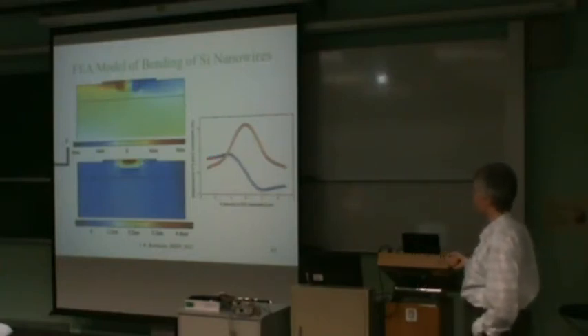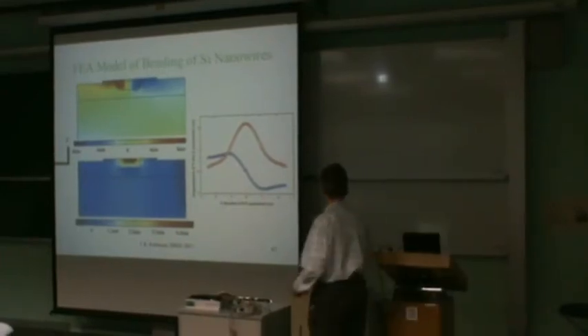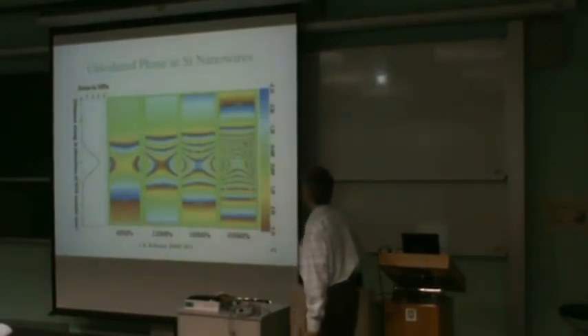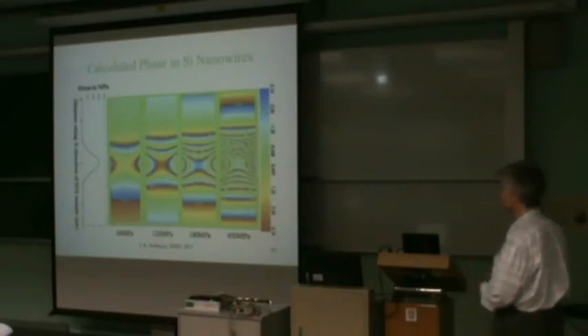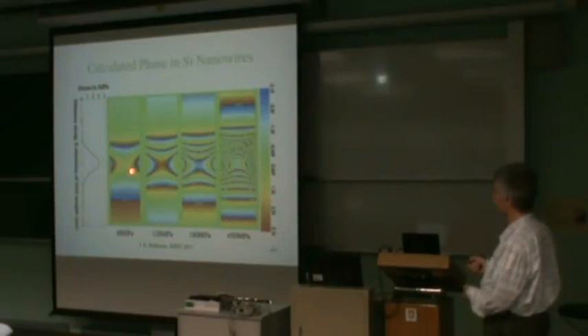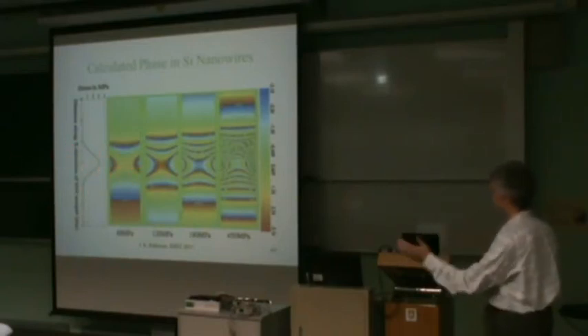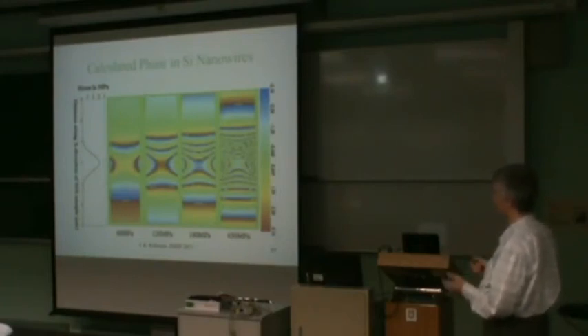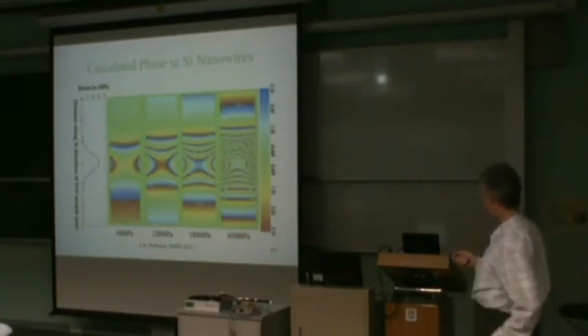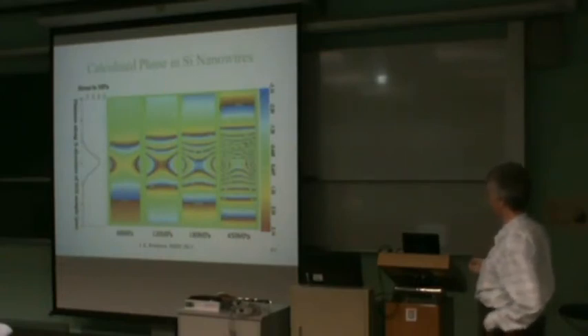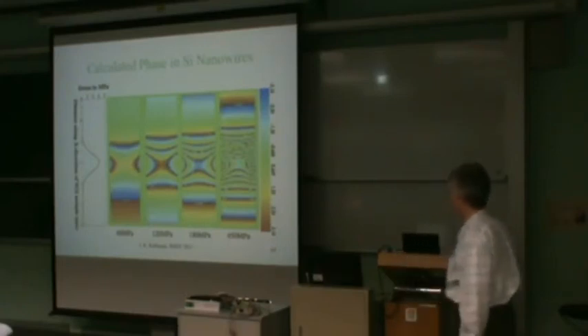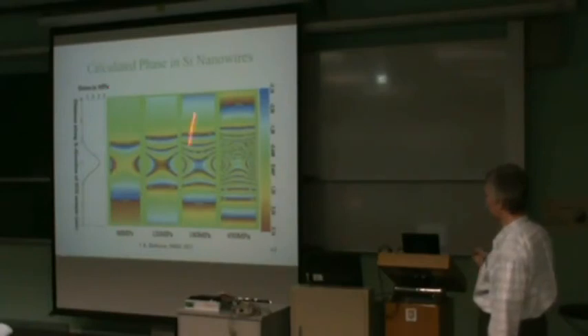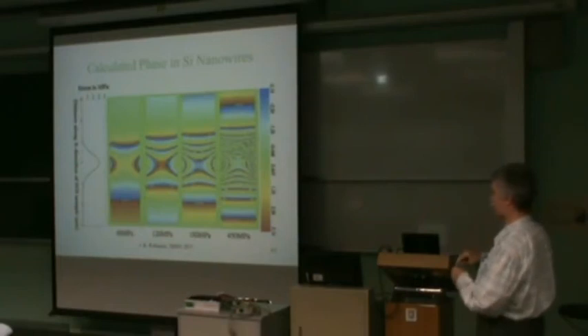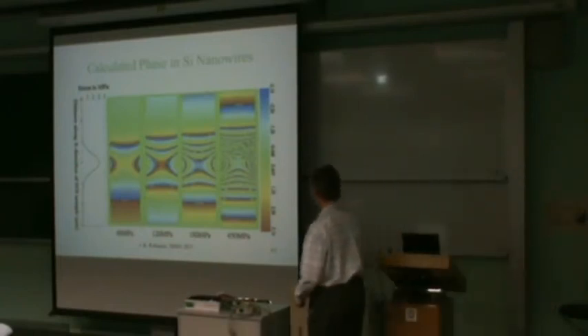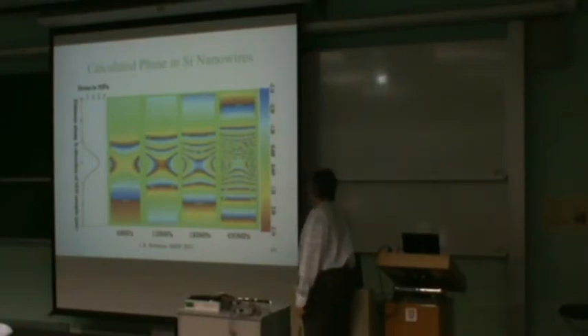So we've got predictions for the distortions of the wire, and then we can just take the Fourier transform of those and look at the expected behavior. So this is showing the distortion converted into a phase. We've assumed a Gaussian-shaped beam profile, and we've assumed that it goes right across the cross-section of the wire, and the mechanical response of the wire has a two-dimensional redistribution of the distortions due to the anticlastic bending associated with this process. So these are just simulations of what is going on as a function of the peak pressure of the distortion that we put into the COMSOL calculation, running up to 450 megapascals for the highest value.